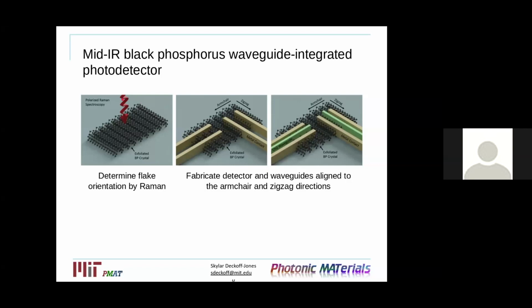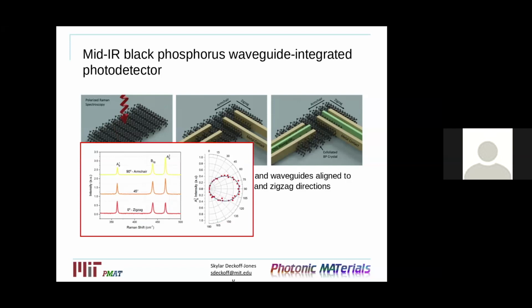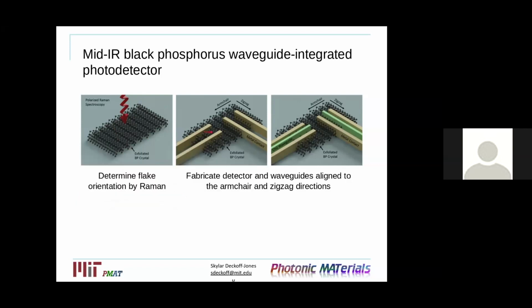And so what we can do is start with a flake of black phosphorus and then characterize its orientation through polarized Raman spectroscopy. This has been developed over the years as a method of determining the crystalline orientation of the black phosphorus. And then once we know the orientation of this exfoliated flake, a small micron-scale flake, we can then very sensitively pattern both the electrodes and waveguides along the flake. And we can even create multiple devices along both directions of the black phosphorus flake to then be able to compare performance of the photodetectors along the armchair and zigzag directions.